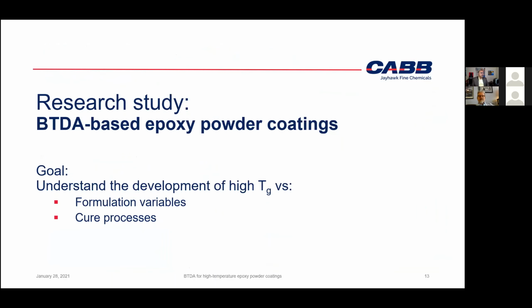So we wanted to do a little research study to systematically try to understand and work with up-to-date commercial resin systems that are available these days, and try to understand what happens to the properties of these kinds of systems based on formulation variables and cure processes. For the properties, we decided to focus on just Tg, glass transition temperature. We figured that's a good indicator of the extent of cure that occurs, of course, temperature resistance, and cross-link density. And many of these properties would be affected by the cross-link density. So we just focused on the high Tg or Tg measurement.